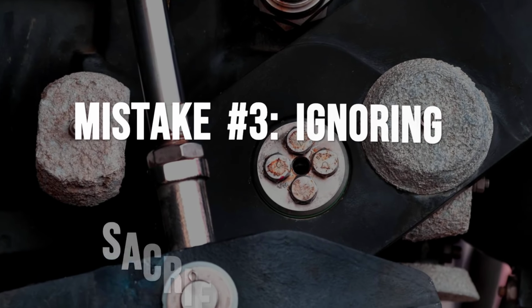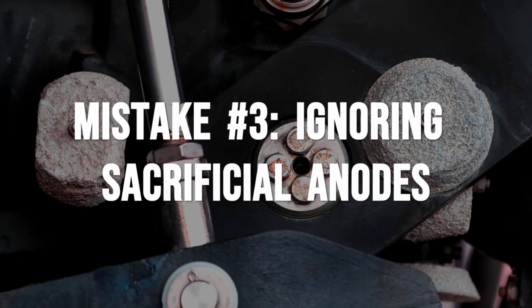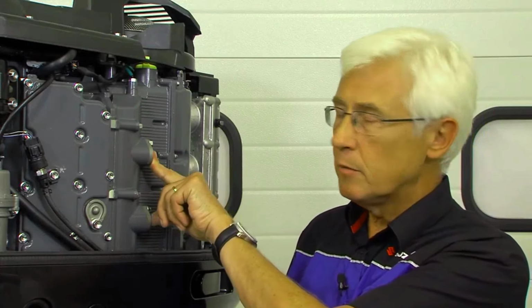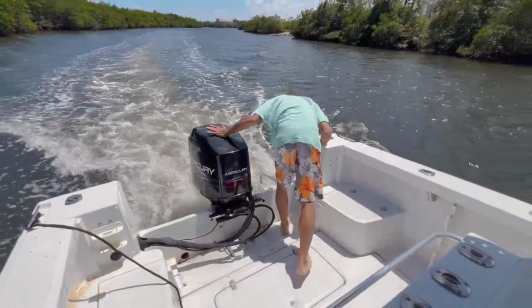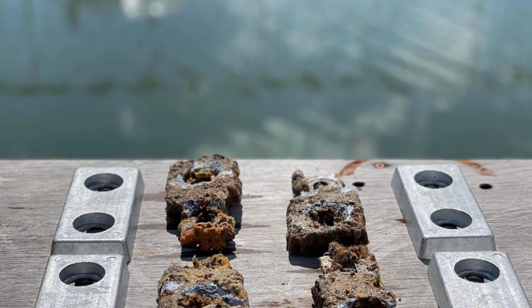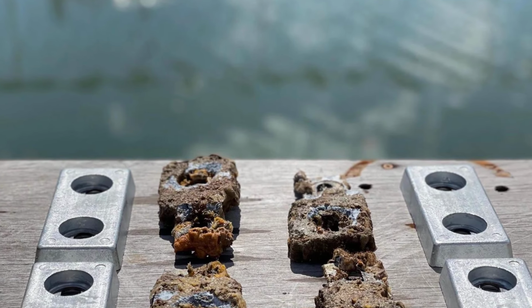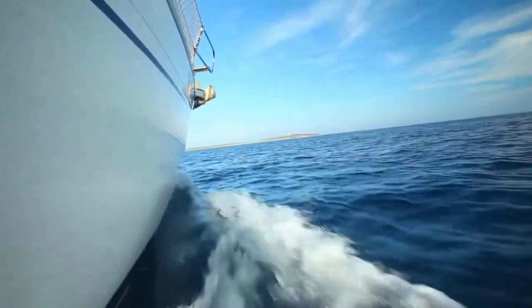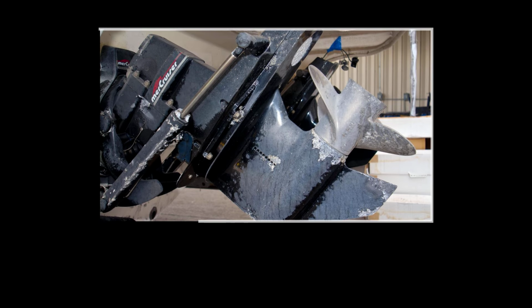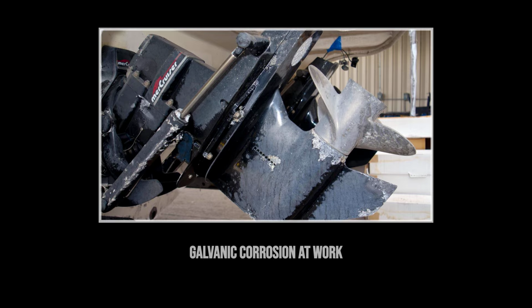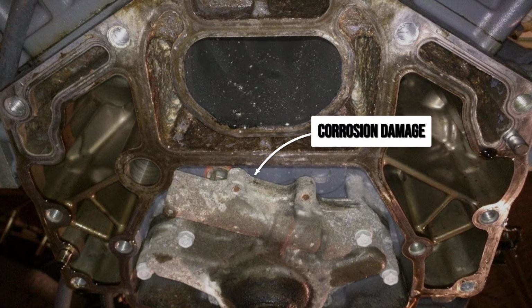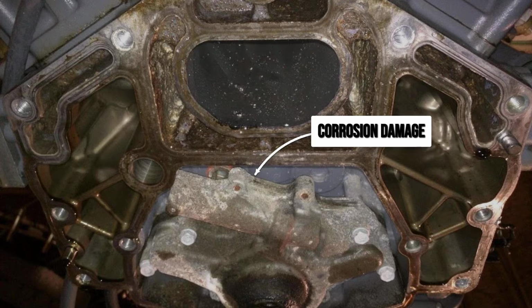Every outboard has sacrificial anodes, those zinc or aluminum blocks bolted to the lower unit and sometimes the powerhead. Most boat owners forget they exist until something goes catastrophically wrong. But what happens when those anodes are completely eaten away and you keep running in salt water? The answer is galvanic corrosion that eats through your lower unit, powerhead, and trim system from the inside out.